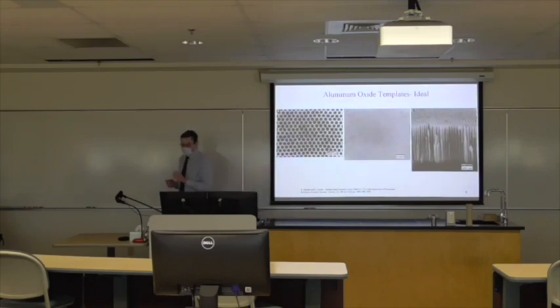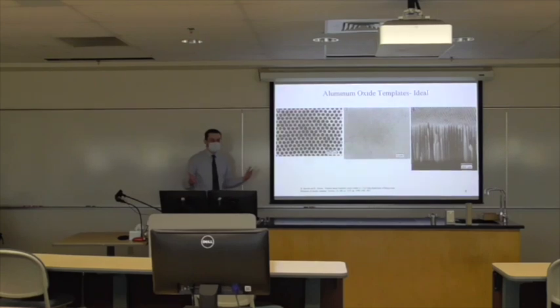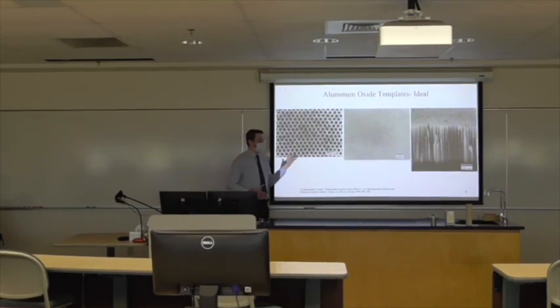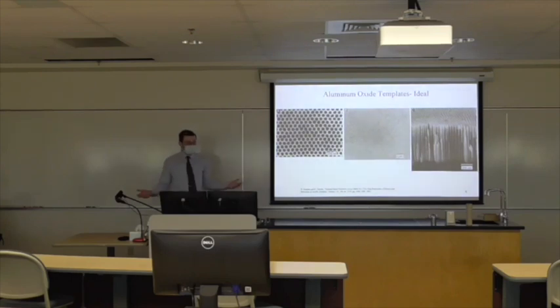Now, these aluminum oxide templates were made under 0.3 molar oxalic acid at 40 volts for 160 hours at 0 Celsius. And those of us who have done work at 0 Celsius for 160 hours or any amount of time, we know that that is a long time to have something at that low of a temperature, and that is in and of itself a challenge.